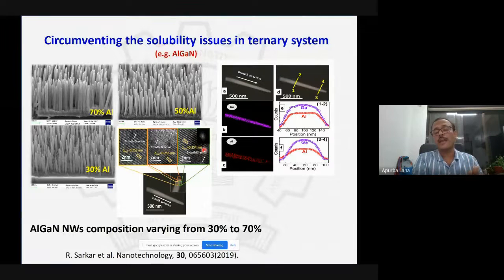All right, so now there was a challenging part at the beginning. I showed you, if you add the aluminum into gallium nitride, the structure becomes very defective. That can also be circumvented by moving into the nanowire structure. Here is an example of the aluminum incorporation in gallium, 70%, 50%, 30%, and you see there is very uniform, atomically distributed aluminum gallium nitride nanowire grown on different substrates. Now, one of the advantages of nanowire is that you don't need a single crystal substrate as was needed for the planar structures.